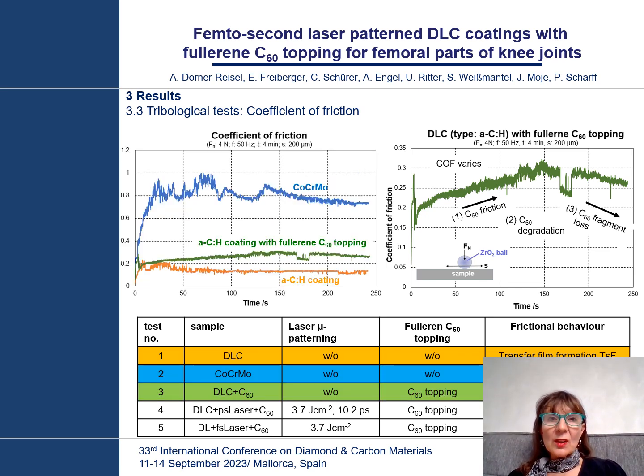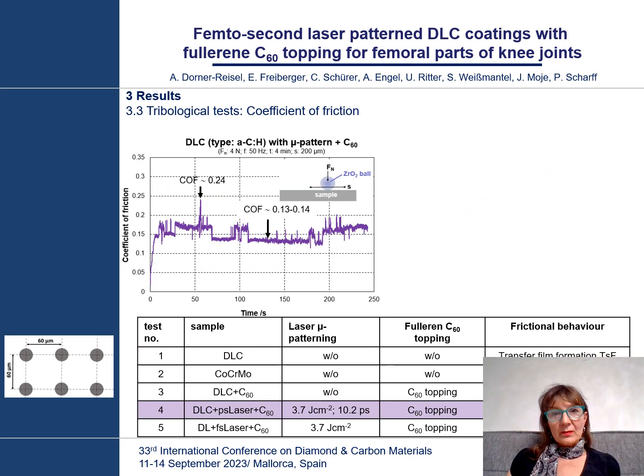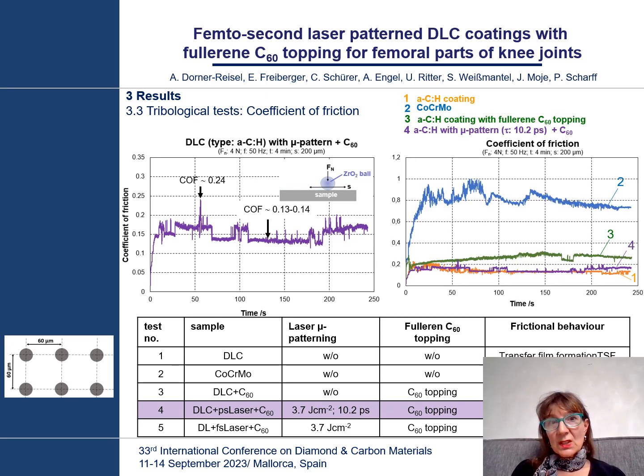However, the level of the coefficient of friction curve of DLC with C60 topping is still much lower in comparison to the non-coated cobalt, chromium, molybdenum coefficient of friction curve. The coefficient of friction curve of picosecond laser micro-patterned DLC with C60 topping is in the range of DLC without C60 and without micro-patterning again. The diagram on the right hand compares different coefficient of friction curves.